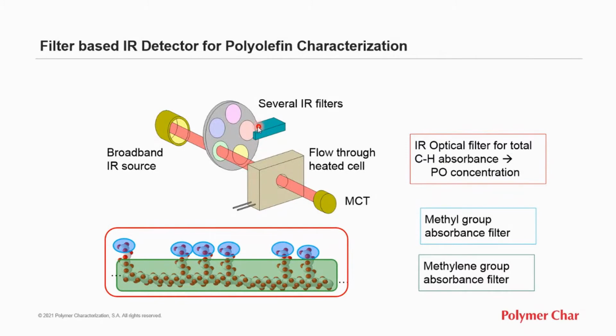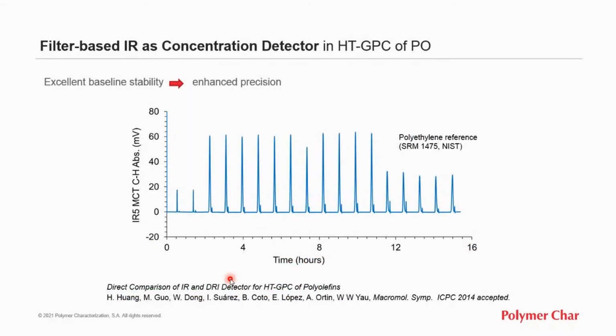In addition, we have specific filters in the same wheel for methyl groups, which are found at the end of the branches due to comonomer, and for the methylene groups found in the backbone of the polymer. From those two filters, absorbance signals are obtained, and the band ratio is proportional to the methyl group frequency, which is related to the chemical composition of the copolymer. IR is a quite robust detection method, giving an excellent baseline, as we can see in this graph.